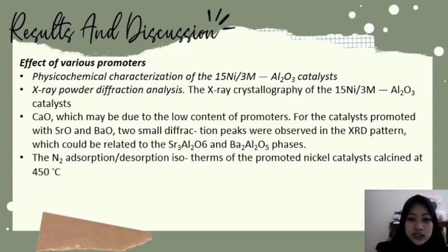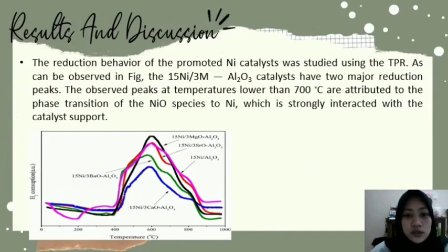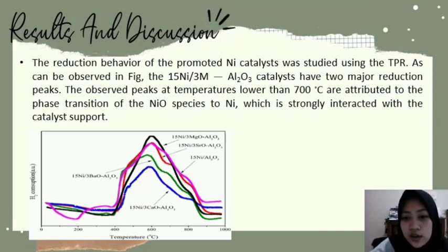The nitrogen adsorption or desorption isotherm of the promoted nickel catalyst calcined at 450 Celsius. Next, the reduction behavior of the promoted Ni catalyst was studied using the TPR that can be observed in the figure. The 15 Ni/3M Al2O3 catalysts have two major reduction peaks. Observed peak at temperature lower than 700 Celsius is attributed to the phase transition of the NiO phase to Ni. It strongly interacts with the catalyst support.